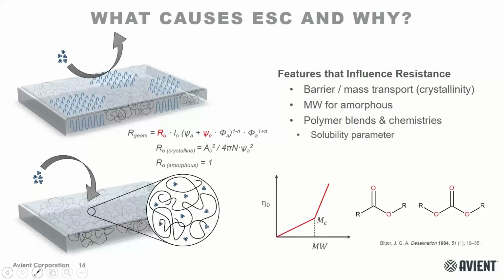And when you go to higher molecular weight, you're going to have more chain entanglement. As long as you're above that critical molecular weight of entanglement, the viscosity, however, is also going to increase. And so this might create some challenges when you're going to process the material. If the viscosity is extremely high, it could also impart more residual stress during the molding process. So there's a little bit of a balance here where you want to have more chain entanglement, you want to have less mobility, but also it becomes more difficult to process.